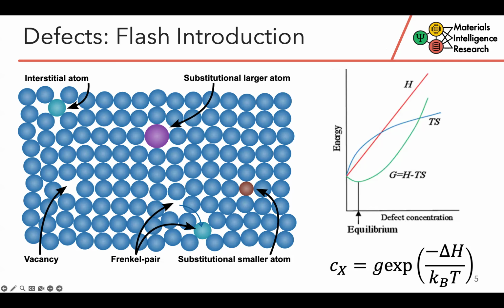And these defects, despite the fact that they always have a positive formation enthalpy, so you can see in the graph on the right, the H here is positive, and this is because they cost energy to form in terms of breaking bonds or forming more unfavorable bonds. They also come with this strong configurational entropy contribution, so TS here in this plot. And so what you find is that at some point these two contributions counterbalance each other, and we get this minimum in the Gibbs free energy at a certain finite concentration of defects.